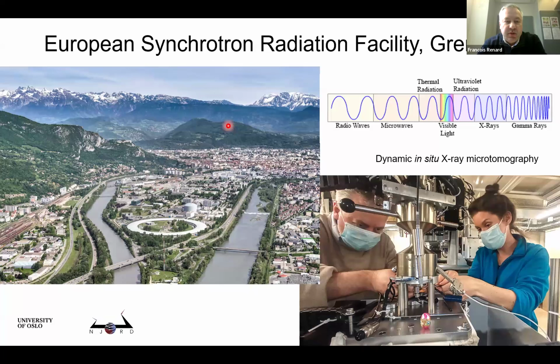So to use this technique, we use a big X-ray source. It's called a synchrotron that produces X-rays. X-rays have a wavelength in the angstrom, sub-nanometer range. So there is almost no limit in spatial resolution of what you can image. There is a limit of data, how much data you can produce. But because of very short wavelengths, we can image rock samples with spatial resolution of sub-micrometers.